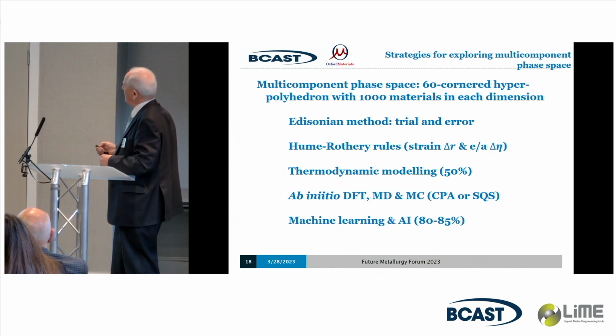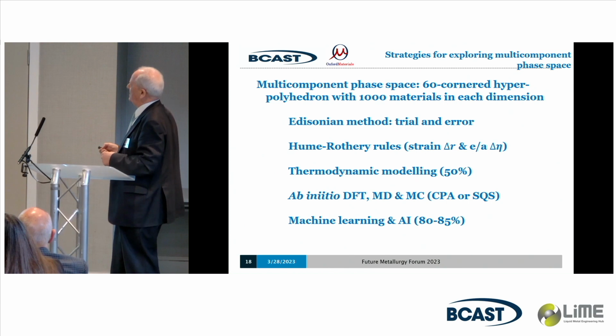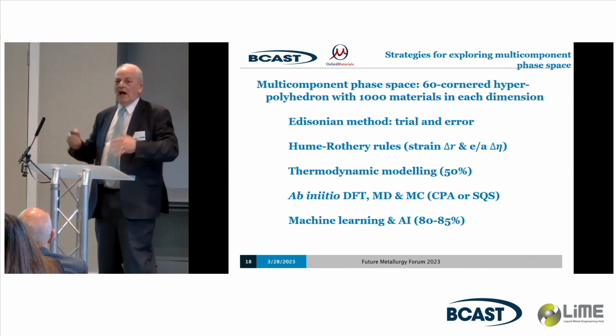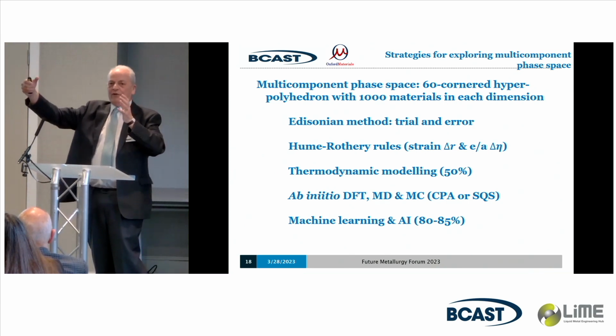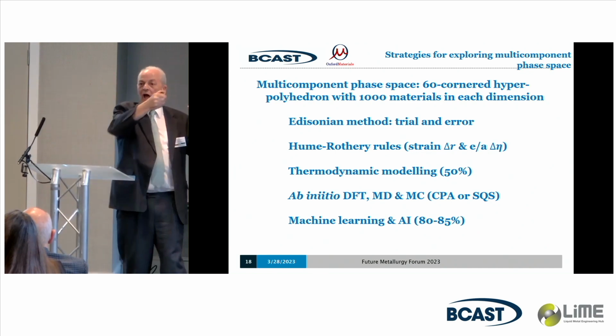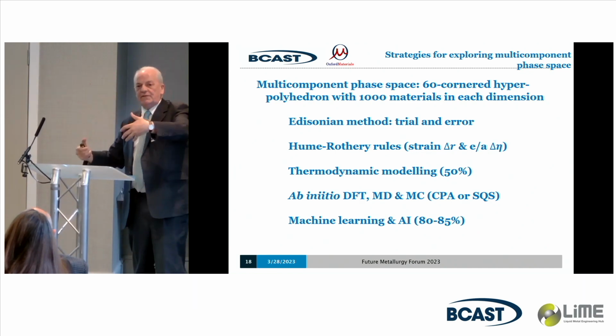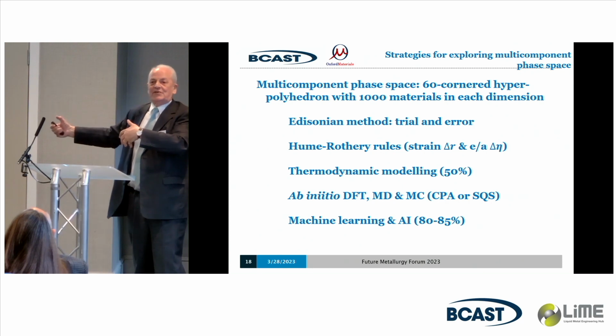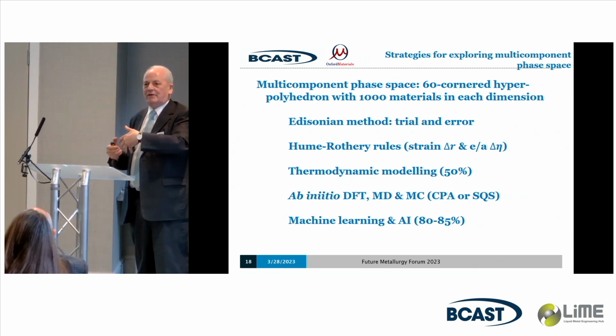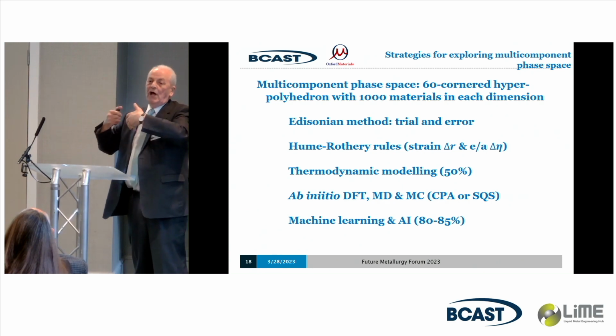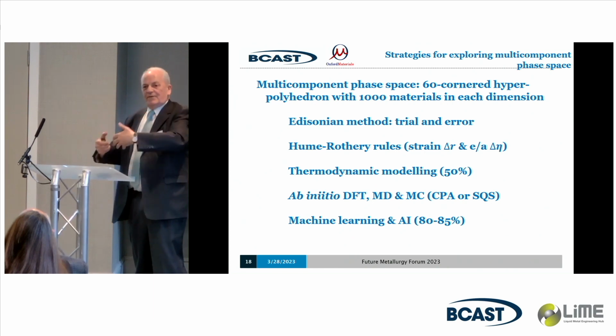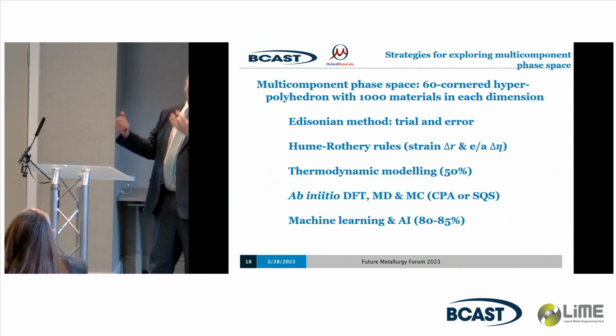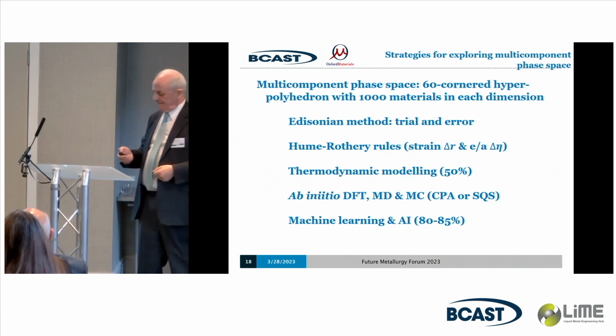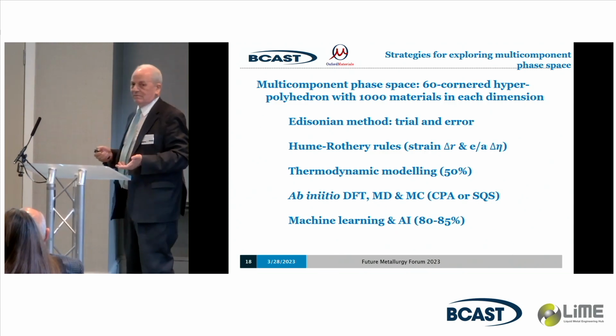So think of multi-component phase space as being a 60-cornered hyperpolyhedron with 1,000 materials in each dimension. It's utterly enormous, and there's gigantic regions of single phases of every crystal structure we know, and between those, there's multi-phase structures, like the first picture we got, of our 20-component material, which have got multiple, not high entropy, fixed stoichiometry compounds, which are very brittle. And they've hardly been looked at. People have ignored those. They've ignored most of the whole space.